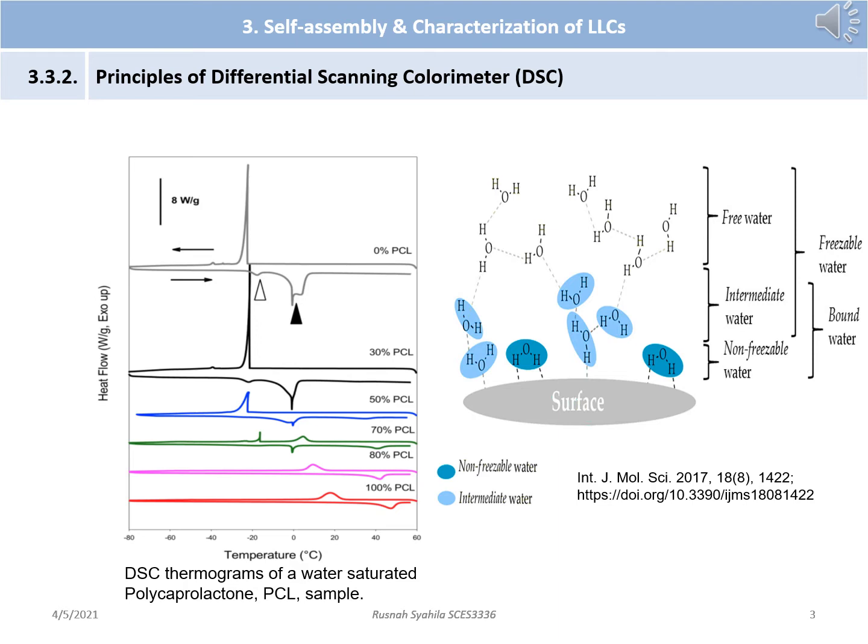Noticeably, a water crystallization peak in the cooling trace at 20 degrees Celsius gradually grows with decreasing PCL content, indicating the hydrophilicity is increasing. Besides the water crystallization, hydrogels containing more than 50% weight PCL are able to maintain the PCL crystallization peaks as well in the cooling cycle. The disappearance of PCL crystallization peaks indicates hydrogels with less than 50% PCL cannot crystallize or possibly merge with the water crystallization peak below room temperature.